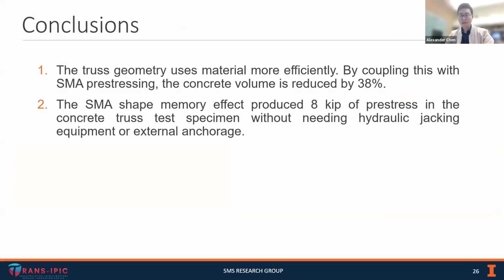In conclusion, the truss geometry uses material more efficiently, and by coupling this with SMA pre-stressing, we can reduce the concrete volume by up to 38%. Also, the SMA shape memory effect produced 8 kips of pre-stress in the concrete truss test specimen without needing hydraulic jacking equipment or external anchorage.